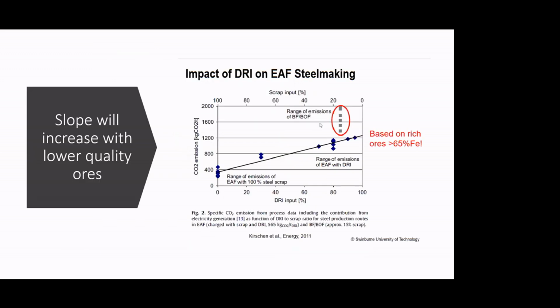This is a slide on the impact of adding direct reduced iron to the arc furnace charge. When there's no direct reduced iron, so they're just using 100% scrap, the CO2 emissions are 400 kilograms. If you remember, the other one was 1800 for a blast furnace, so that's a considerable reduction. As you increase the direct reduced iron content, those emissions go up, and that's based on ores that are 65% iron. If they use ores that are less than 65% iron, then basically you've lost your emissions advantage.